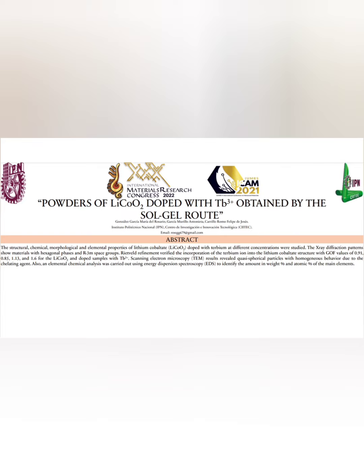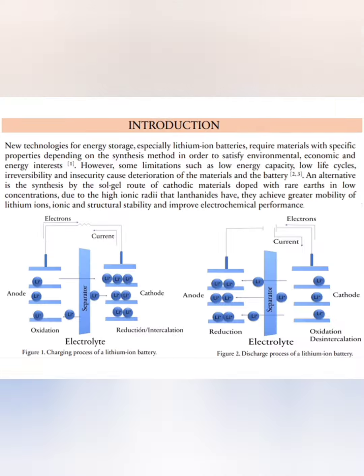Scanning electron microscopy results reveal quasi-spherical particles with homogeneous behavior due to the chelating agent. Also, an elemental chemical analysis was carried out using energy dispersive spectroscopy to identify the amount in weight percent and atomic percent of the main elements.